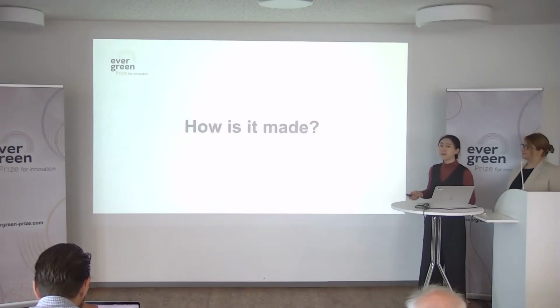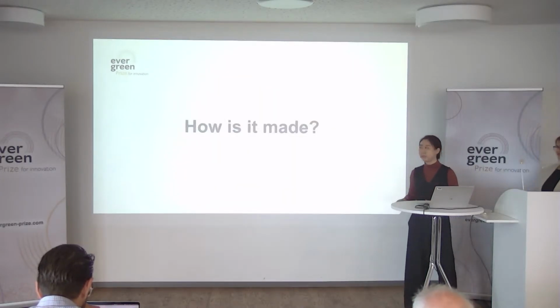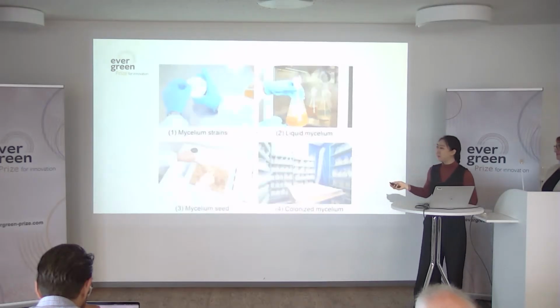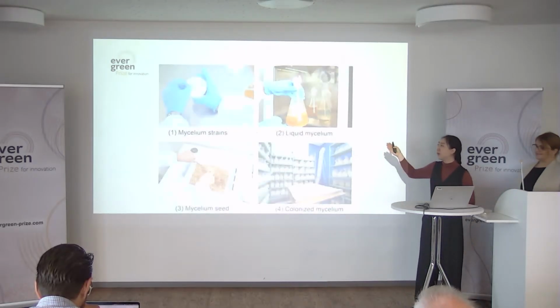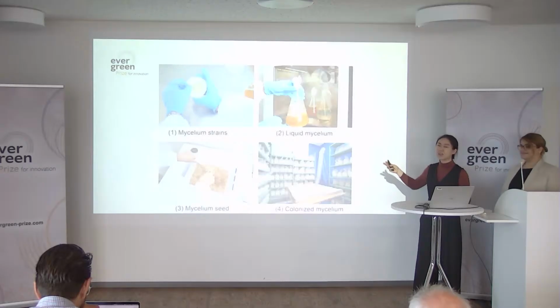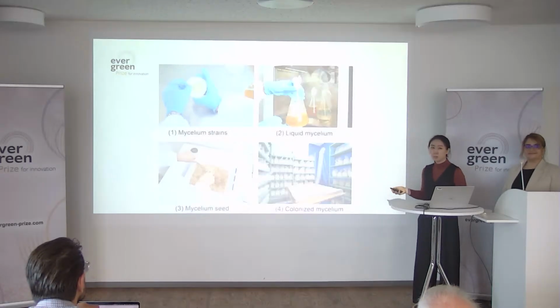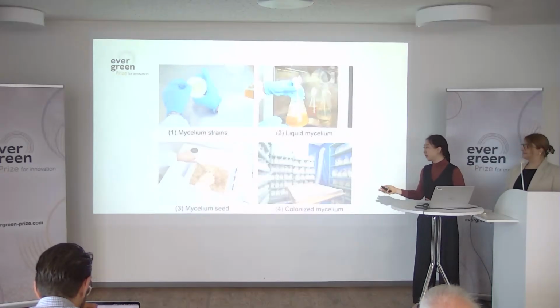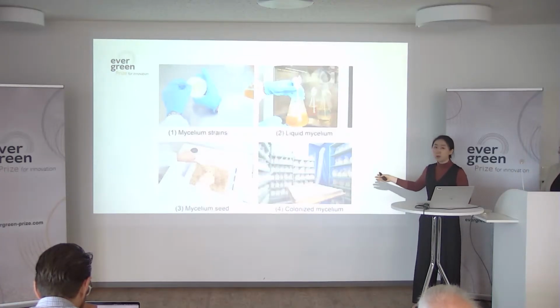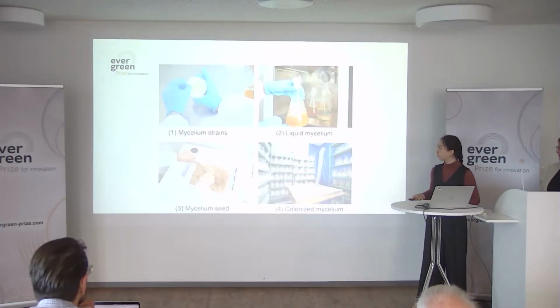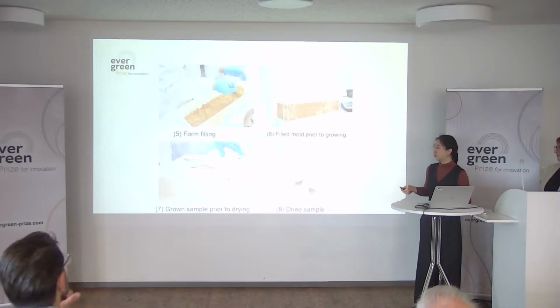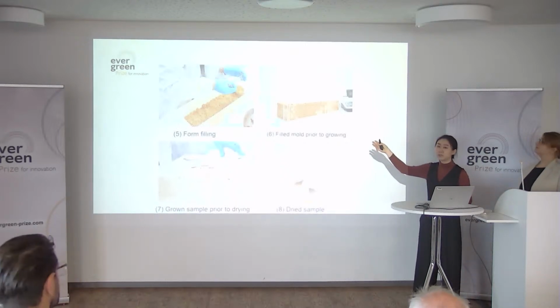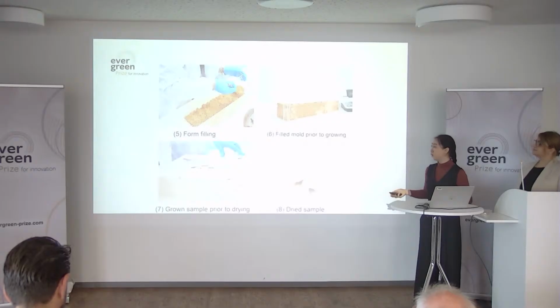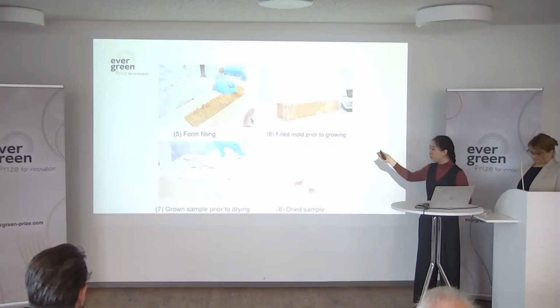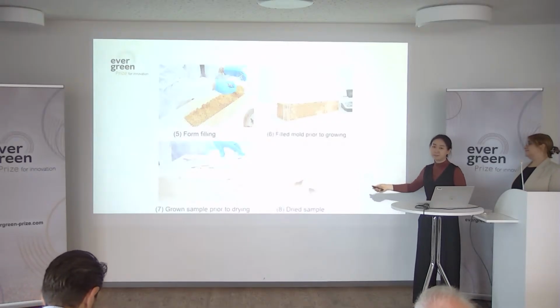You may be very curious, how is such an amazing material made? Well, here's a summary. Basically, we start with culturing and selecting the mycelium strain, something that we think actually works best. Then we seed the mycelium into the solid substrates that we want them to grow in. After that, we leave them to grow and fully colonize the substrate. When the substrate is ready, we fill them into these forms so that we can shape them in whichever way we want. After they are fully grown, we demold them and we dry them.